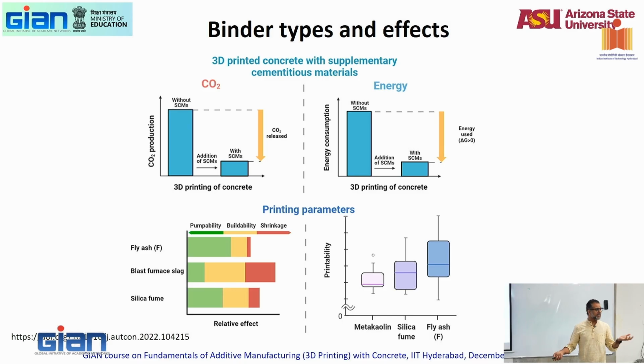Really, don't try a clay-based material in printing unless you really love clays and you have designed the mix for an LC3 or a clay-like mixture. Otherwise, the cohesiveness of that will make extrudability a really, really difficult task. It's not that it's not possible. The water demand also is going to be very high. When the water demand goes very high, you will either have to use lots of admixtures or lots of water. Both are not good. Lots of water is not good for strength. Lots of admixture is not good for economy of your mix. So again, a few things to remember when you look at all those binder types.